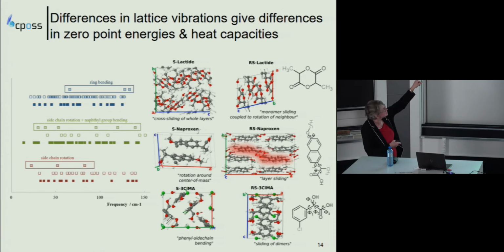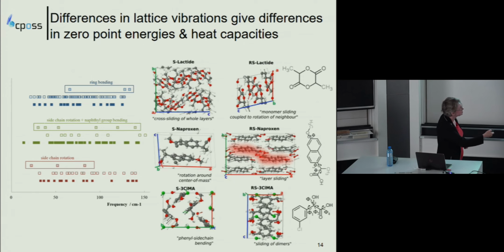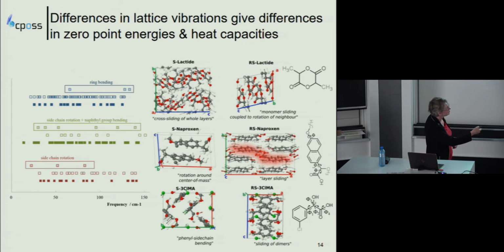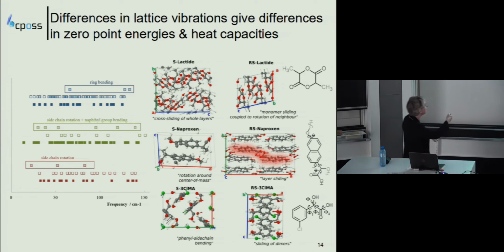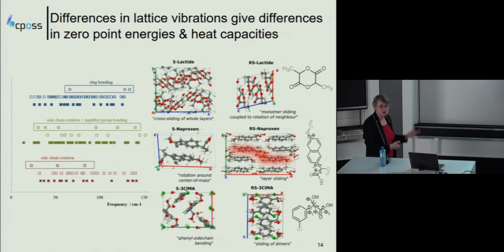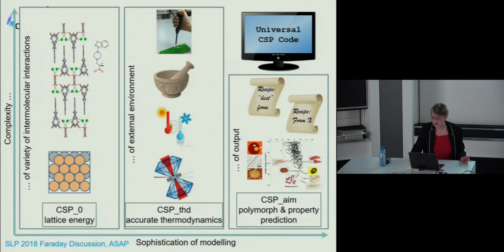For each of the series, the top in the square are the molecular frequencies, and you can see that some of the molecular frequencies are down in the low energy region of less than 150 centimetres to the -1 to a different extent, and then you've got the frequencies at just k equals 0 modes, phonon modes, they've got different crystals. And so, for instance, here in naproxen, which is a drug molecule, in the racemic form, you've got a very low energy sliding of the two layers across each other, giving you a very low energy frequency there. So it's not surprising that you do have differences in 0-point energies and differences in the heat capacities as a function of temperature between the two structures.